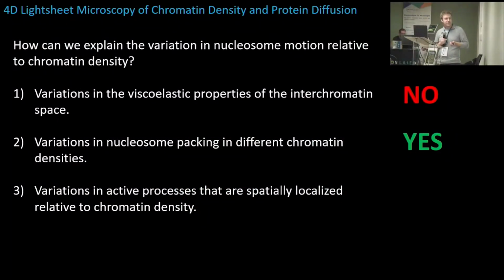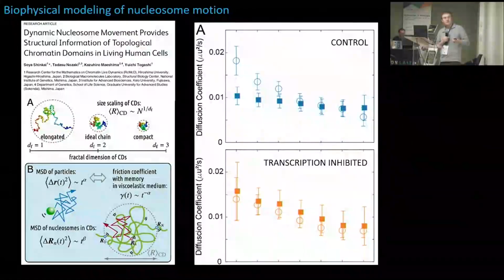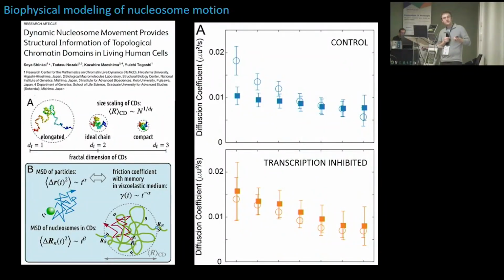Okay, so yes, there are variations in active processes that are localized in different chromatin density regions, and we wanted to see what this does in relation to our model. This is an example where this is our normal control cells. This is what the model predicts based on purely thermal forces, and this is our transcription inhibited experimental data, and this is what the model would predict based on purely thermal forces. So if we inhibit the active process of transcription, the entire nucleus seems to behave like a thermally driven Rouse polymer, but otherwise we don't. If we want to model this from a bottom-up standpoint, we need to take into account a stabilization effect of nucleosomes in these active transcriptional compartments.